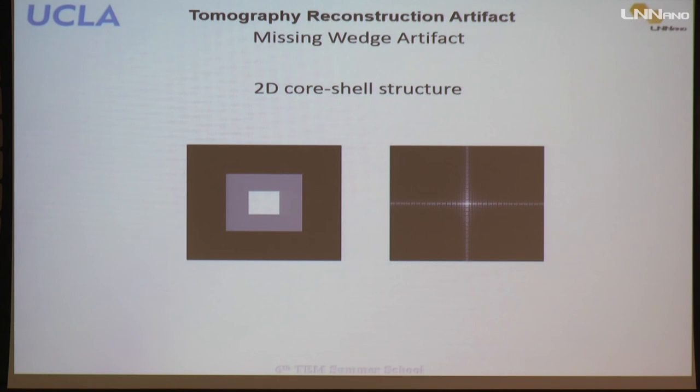And this is a 2D core shell structure, like core shell nanoparticles or something like that. I just simulated it as binary. So in the center, it's bright, with slightly lighter material surrounding it, and background. And this is the Fourier transform. And you can see there are sharp edges in our model. And a sharp edge